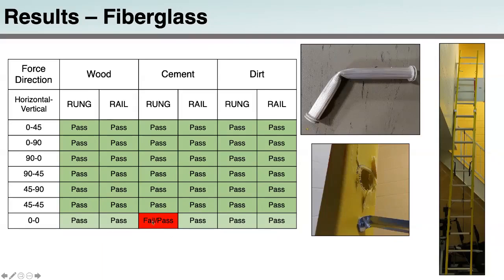So you can see here that this is where the ladder failed, and then for the remaining conditions that we tested on that new rung, it passed successfully each time. So this kind of leads us to believe that it wasn't just a one-off that it passed or failed. It was likely due to the 30+ prior impacts that that one rung had endured.